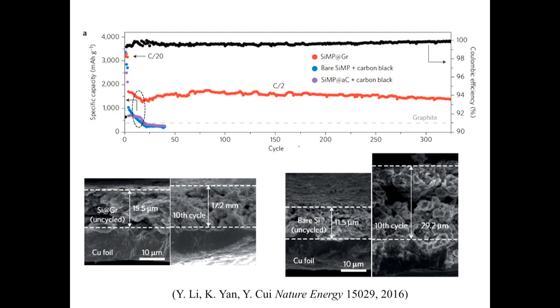And not only do you have a stable capacity, if you look at the electrode on metallic foil, this is a cross section. In the beginning, 15.5 micron becomes 17.2, only expanding a little bit at the electrode level. But the bare silicon particle without this graphene cage will be broken, expanding a lot to 30 micron, 3 times. This is the killer to your battery. You don't want your electrode to expand. If the electrode expands, it's going to squeeze your packaging and leak out, and your packaging will be broken. You leak out the electrolyte. That's dangerous. So this now also solves the electrode level expansion.